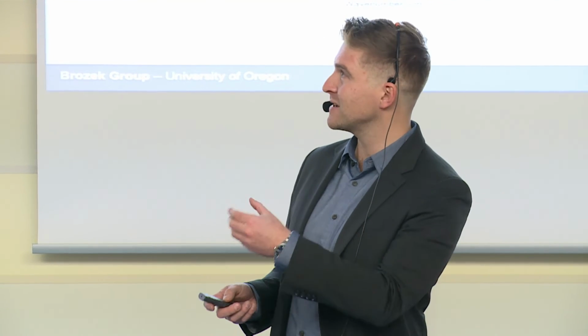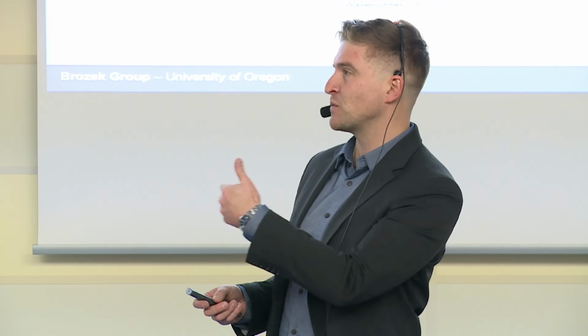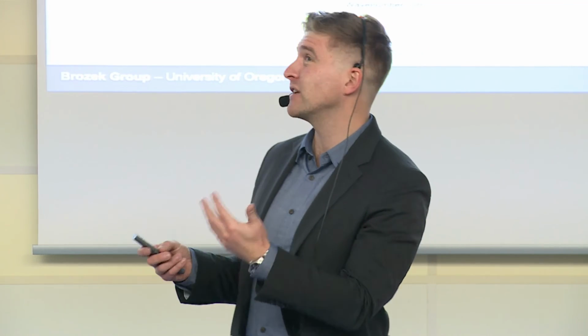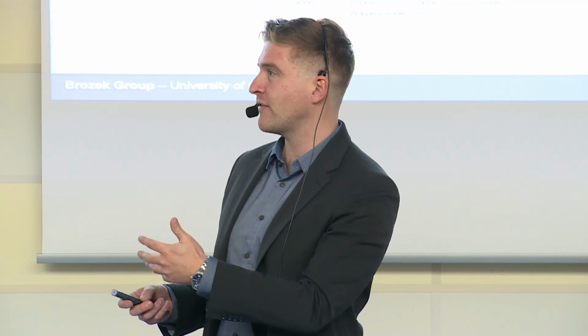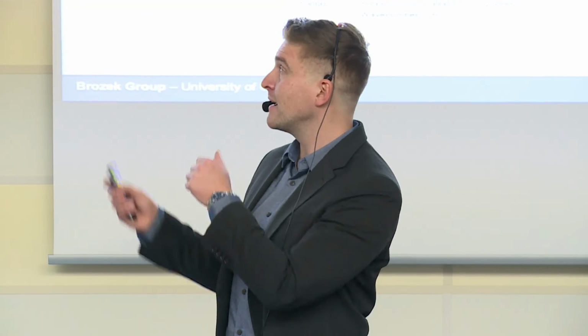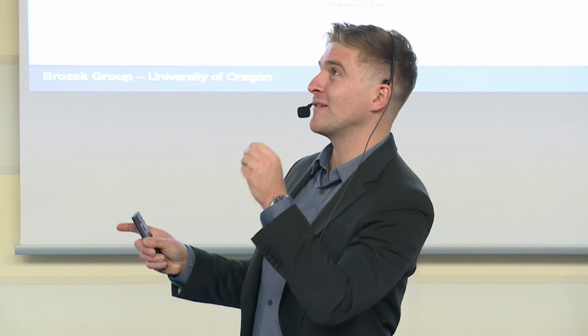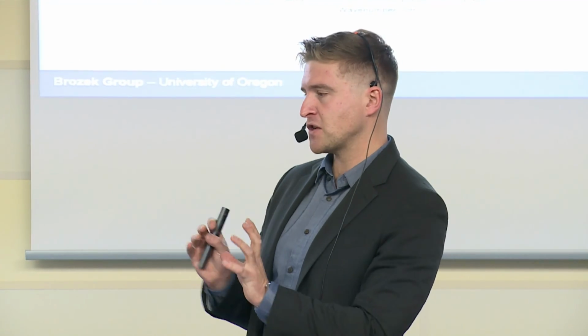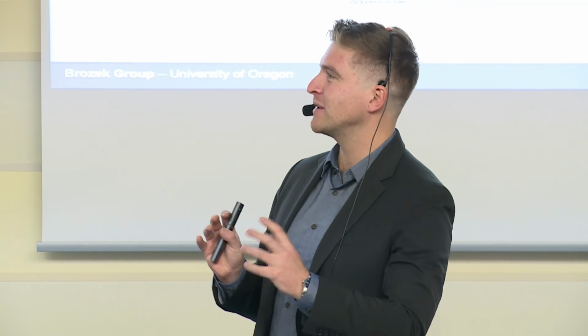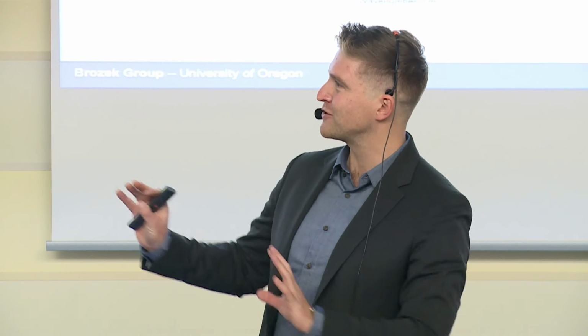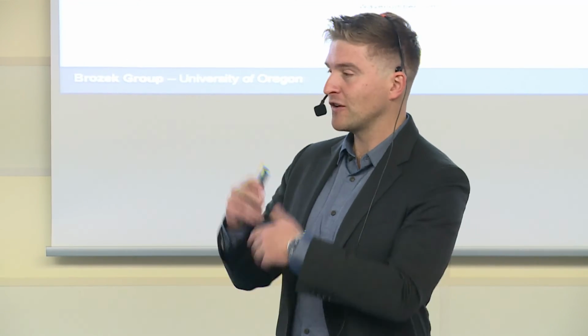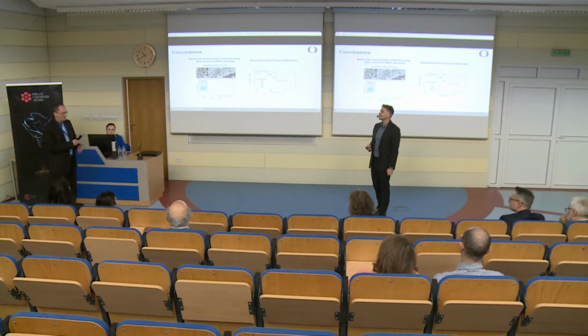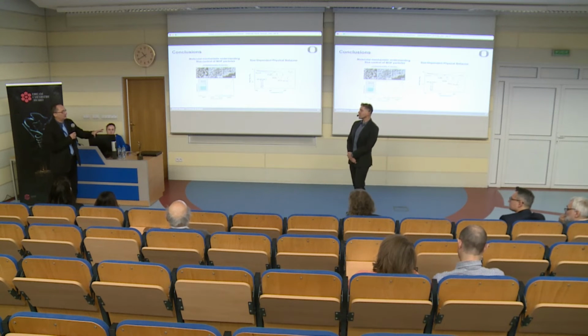I think it's going to allow us to form covalent linkages with the polymer, or maybe heal in response to a break. Just the fact that you have this reversible on-off, I think, is actually going to help in that regard. I hesitate to call that bound and unbound. It really is just, this is why we call it the flexibility constant. They're able to rearrange in response to temperature without falling apart. So it would be healing, right? Even if the membrane locally breaks at the nanometer scale, it would.